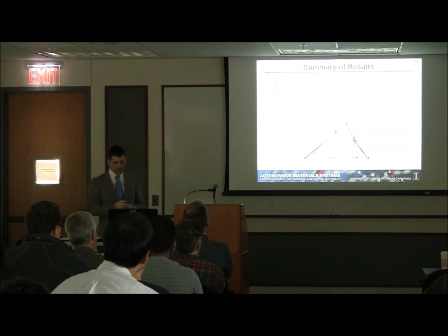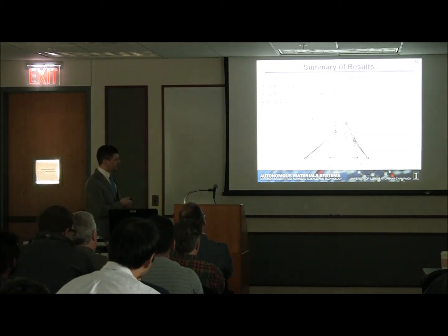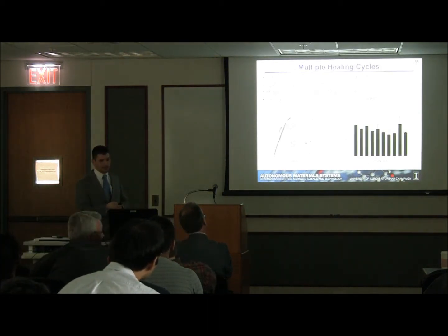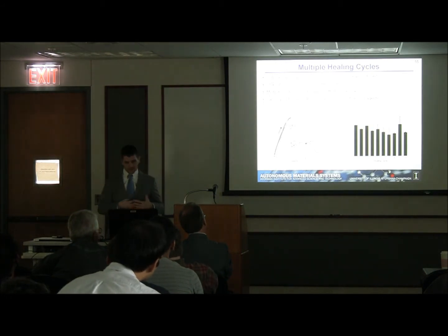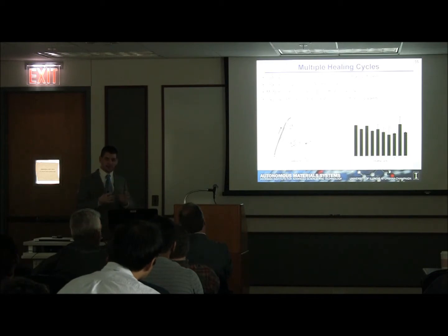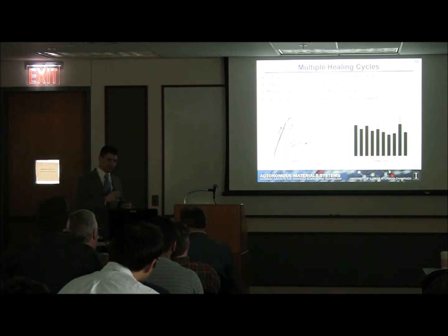So we can take the best performing healing cycle from our single heal tests and actually apply that over multiple healing cycles. If we use multiple healing cycles, we have to be sure to keep the channels clear during each one of these cycles. So when I'm doing these multiple healing cycles, we're actually purging the channels during the healing event between each one of these cycles. That's one distinct difference between the two methods.